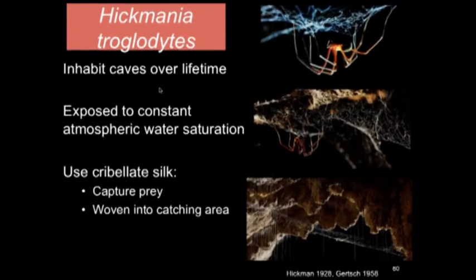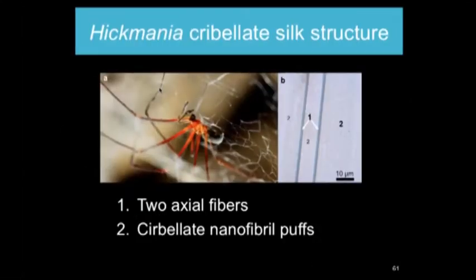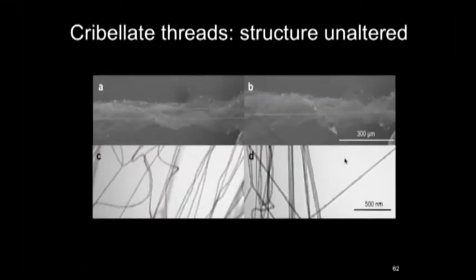So their silk is quite similar to what I showed. Here's a photo that we took, the spider in the web. You can see that the cribellate silks are these dark, more bold looking fibers, and when they're fresh, they look a bluish color. This is a polarized image. Using light microscopy, you can see that there are these two fibers, and the nanofibril puff, which isn't in full focus, but it's this kind of pleated looking background that surrounds the fiber. And we showed that our methods do not change or cause the fiber to collapse. These are SEM and TEM images in dry conditions and wet conditions, where we show pretty obviously that these fibers don't collapse on themselves in either condition, which is great for our study because we can show definitively that it's unaffected primarily by our methods.